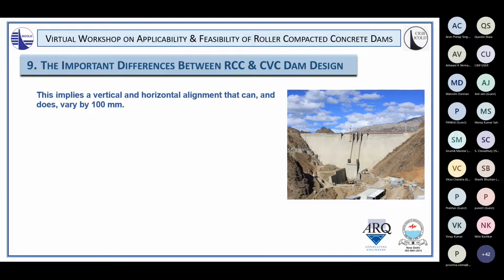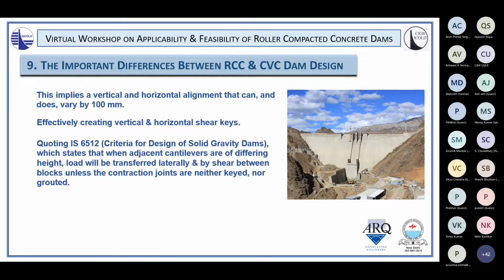And this implies that we have vertical and horizontal alignment of our induced joints that varies by 100 millimeters, effectively creating vertical and horizontal shear keys in our RCC. And if we look at Indian Standard 6512, which is the criteria for design of solid gravity dams, this states that when adjacent cantilevers are of differing height, load will be transferred laterally and by shear between blocks unless the contraction joints are neither keyed nor grouted.